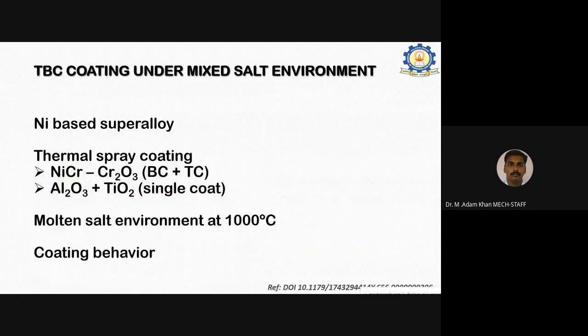Okay. So what I have done in my research, I have done two coatings. One is alumina titania single coat, not a double coat like a bond coat and top coat. I have done one more, nickel chromium and chromium oxide. I have excluded alumina or any sort of ceramic forming oxides. If I have the conventional nickel chromium aluminum yttria, when it takes to the oxides, this aluminum will form Al2O3. If yttria is there, Y2O3 will form. So I have just avoided taking these as a TGO.